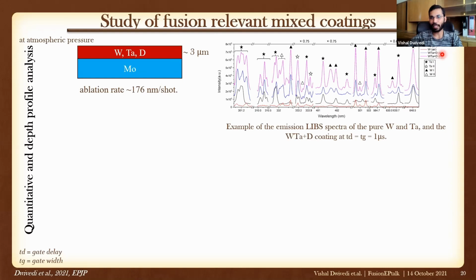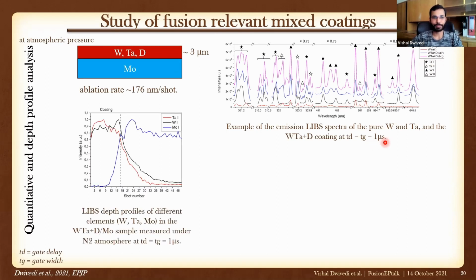So we measured in air firstly, but we don't get enough signal for deuterium. So we try to measure under nitrogen atmosphere. And we can see in this spectra tantalum 1, tantalum 2, and tungsten 1, tungsten 2 lines. This was measured for 1 microsecond delay and gate time.